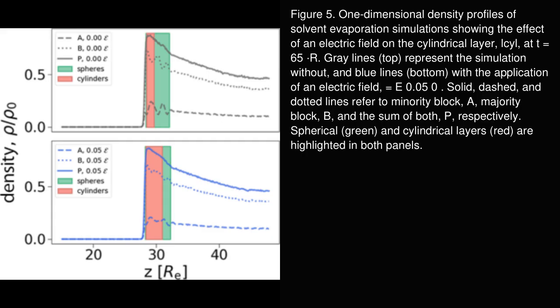The authors note that this increased cylindrical layer thickness results from the reduction of the polymer density at the order-order transition, enabling cylinders to appear earlier and grow faster during solvent evaporation. Furthermore, this system features a shallow composition gradient, providing a conducive environment for observing significant changes in domain size induced by the field. In summary, Figure 5 illustrates that electric fields enhance the growth of perpendicularly aligned cylindrical microdomains by shifting the thermodynamic and kinetic conditions during evaporation, corroborating previous experimental findings, and supporting the theoretical model of dielectrophoretic alignment.